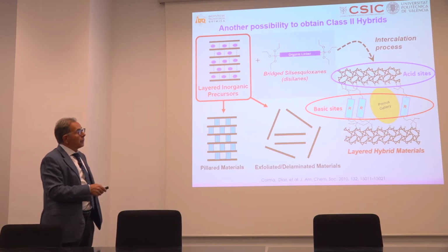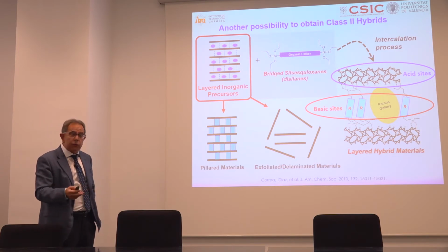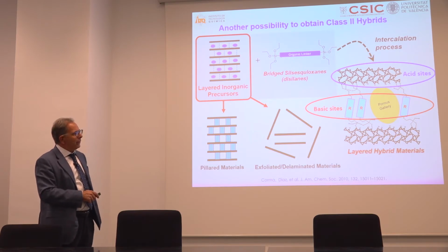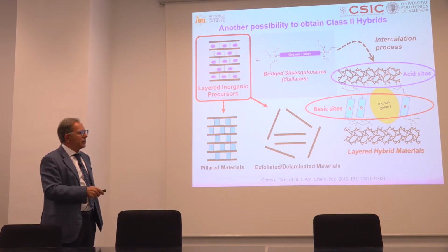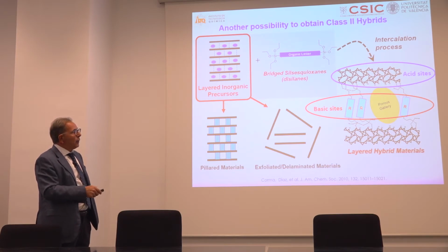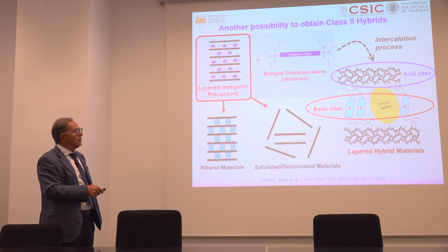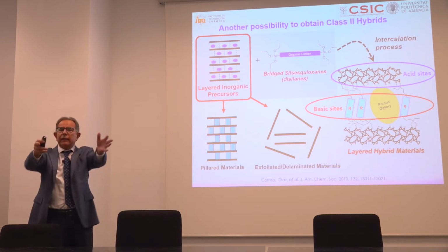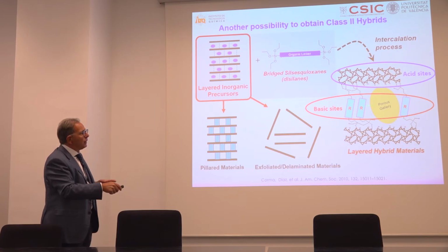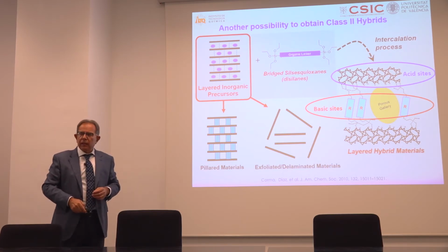So we took a 2D zeolite, ITQ-2, the first 2D zeolite that was ever prepared, and here we have the inorganic part. We have the micropores, zeolitic micropores, in where we can introduce here either acid or basic or metal sites. Then in between the layers, we take now one organic with this disilane, we anchor the 2 layers, and we pillar it with those ones, and we introduce basic sites in this one. We'll have galleries in where the molecules can diffuse, and they will have accessibility to the basic and to the acid site. So we have 2 sites.